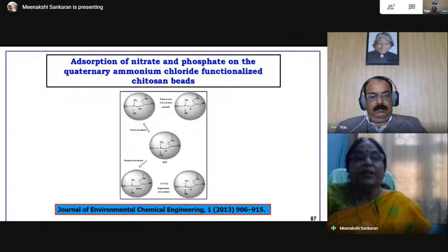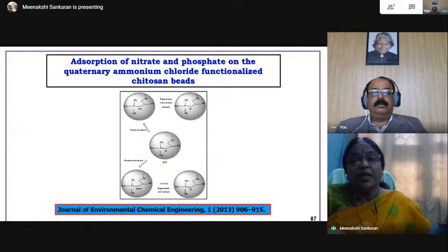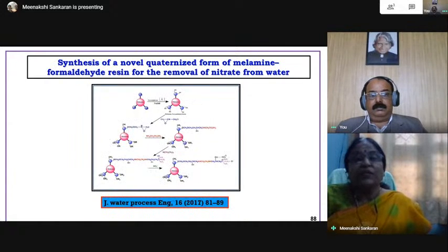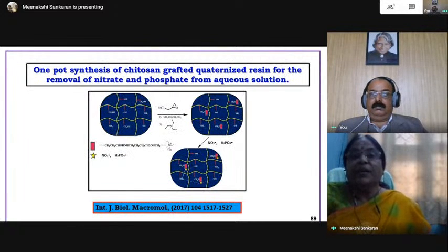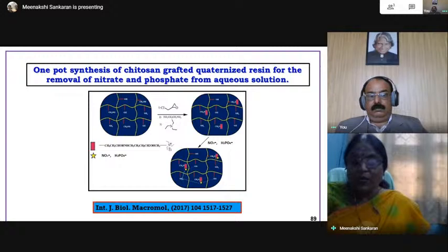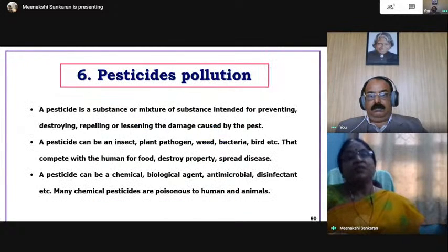And we have prepared quaternary ammonium chloride functionalized chitosan beads. For the first time we have made this type of material for phosphate and nitrate in our laboratory. Nowhere has it been reported. And this is also one of the novel materials, using melamine formaldehyde resin for the removal of nitrate from water using chitosan also. So in this also, we are the pioneers in the synthesis of this type of materials for the removal of nitrate and phosphate. And chitosan grafted, we have grafted quaternized resins onto the chitosan surface so that it can remove more nitrate.